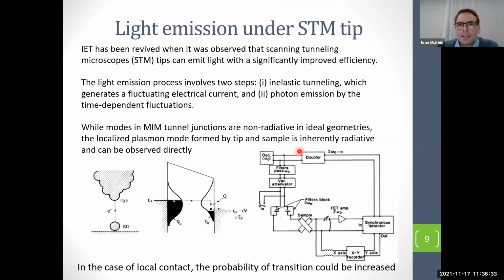The simplest way to organize a tunnel gap, and you remember that the width of this gap is about 1 nanometer, is to use a scanning tunneling microscope, and inelastic electron tunneling was revived when it was observed that an STM tip can emit light with significantly improved efficiency. How it works: if you consider a metal substrate and an STM tip, due to charge distribution there is a second, mirror image of the tip. So the system is equivalent to two metal tips, which actually is a conventional optical bow tie antenna.